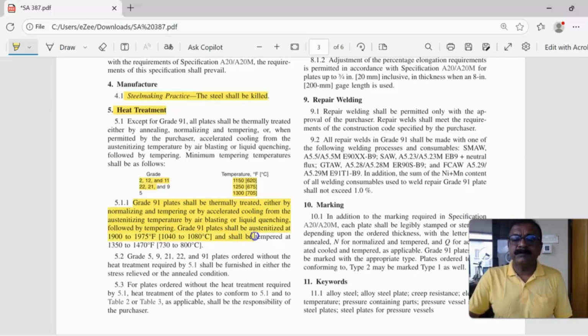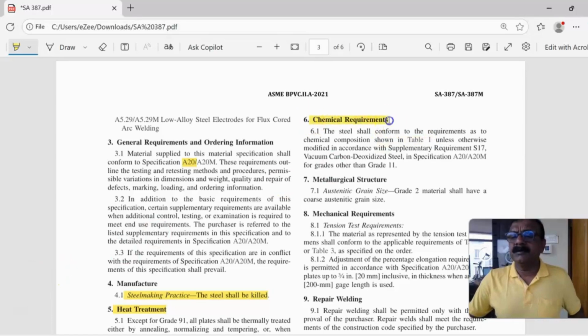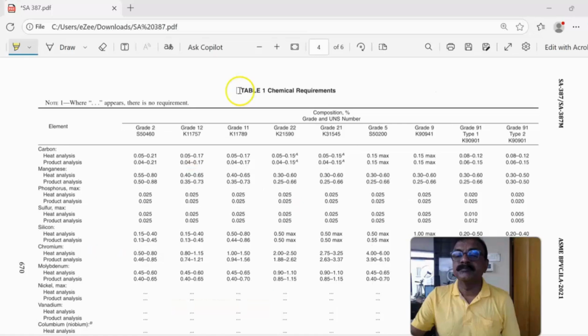Grade 91 plate shall be austenized at 1040 to 1080 degrees centigrade and shall be tempered from 730 to 800 degrees centigrade. Chemical requirement shall be as per table 1. This is table 1 for chemical requirements.